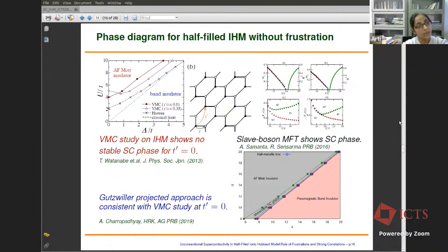They also did a study in the presence of second neighbor hopping, but that second neighbor hopping was turned on only on one of the sublattices, not on both the sublattices. So we cannot compare their results for T prime non-zero with our calculations, because we turn on the second neighbor hopping on both the sublattices, as it should be done. The main point here is, at least in the absence of the next neighbor hopping, our Gutzwiller projected renormalized mean field theory as well as the DMFT plus CTQMC provide a phase diagram which is qualitatively consistent with the variational Monte Carlo study.